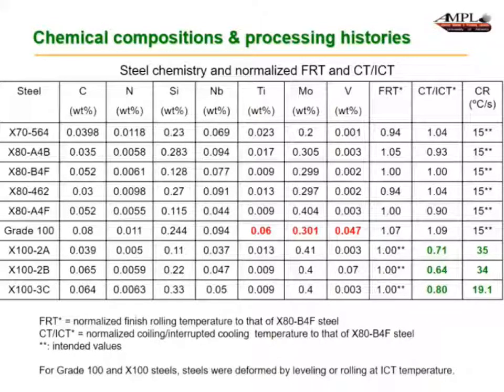Well, to do that, you've got to be able to collect these particles from a fairly well representative sample of the steel and be able to then characterize them. And so that's what was done here with these various steels indicated here. The one difference here, you see 3 X100s. All of the ones above the X100s were done in the steel mill. The X100s were done at the pilot mill at CanMet. At that time, it was in Ottawa. So there's a marked difference between the 2 in terms of the precipitates, as you will see.